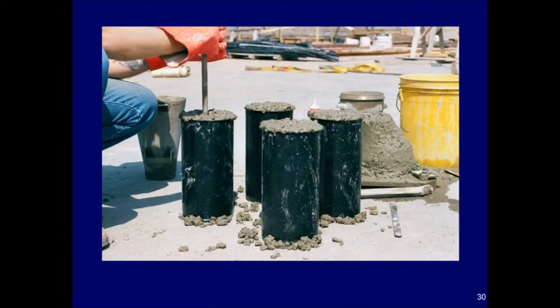As an example of why phi factors are used in design, consider a concrete mix that is to be used in a beam of a cast-in-place concrete building. The engineer has specified a compressive strength of 4,000 PSI at 28 days. At the time the beam is cast, specimens of the concrete mix are collected and are subsequently tested in accordance with the provisions of Chapter 5. It's found that a single test yields a strength of 3750 PSI.